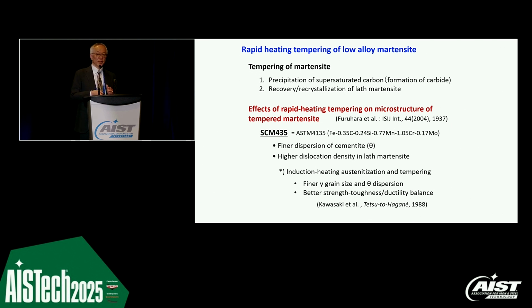We can use induction heating in the line, and this was already found in the 80s by Kawasaki. By combining both induction austenitization and induction tempering, we can get a finer grain size and also a better strength and toughness balance. So this kind of controlled rapid heating is very good for better properties.